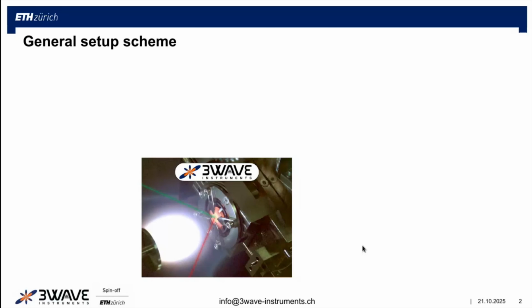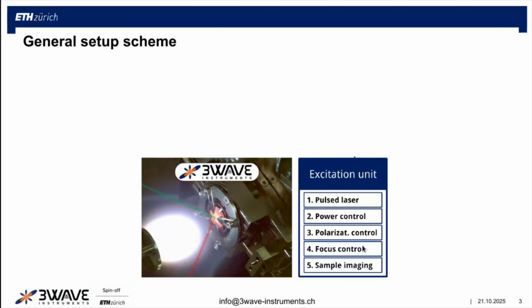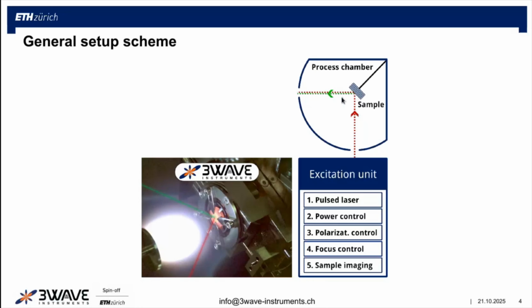And so as Manfred already showed you, our setup is basically built onto 2 optical setups encapsulated in shoebox-sized boxes. And let me briefly start with the excitation unit, which holds our pulse laser. Here we also have the option to change the incident power. We can control the polarization very finely with sub-degree resolution. We can set our focus from the factory out. So whatever the size of your chamber is or the experiment you want to drive with, we can control that the focus is on the sample position finally. And we have a nice feature that gives you illumination and imaging of the sample in the chamber, so that you can directly see if the laser beam nicely hits the sample that is mounted on your heater.